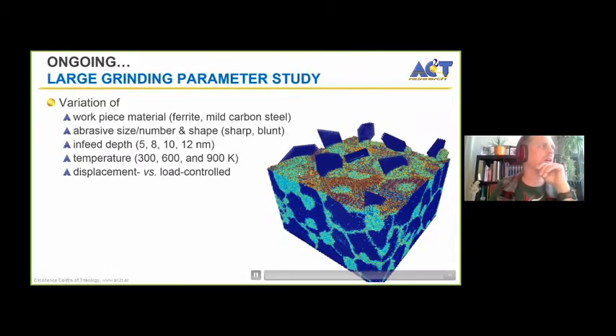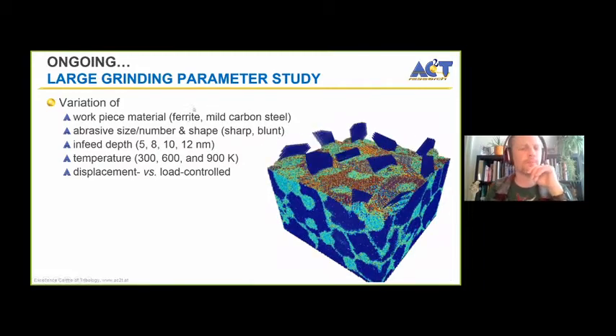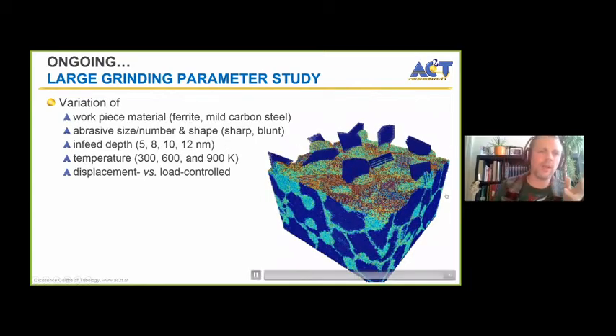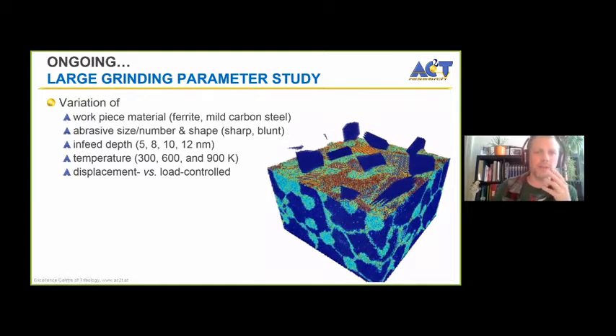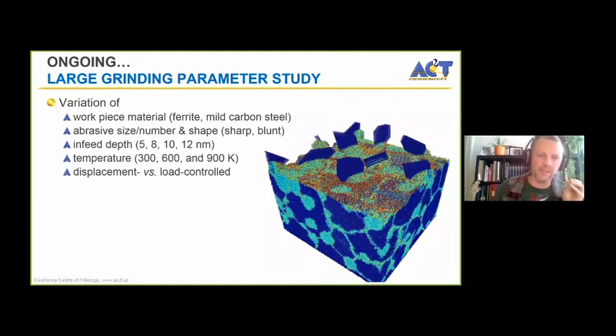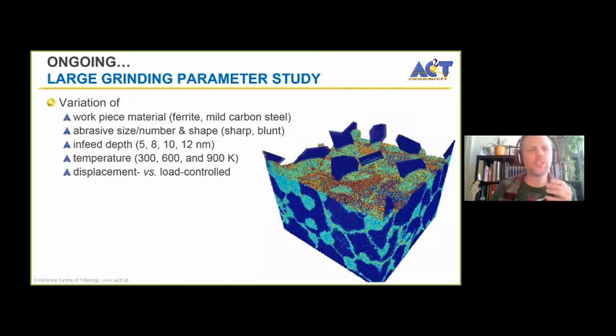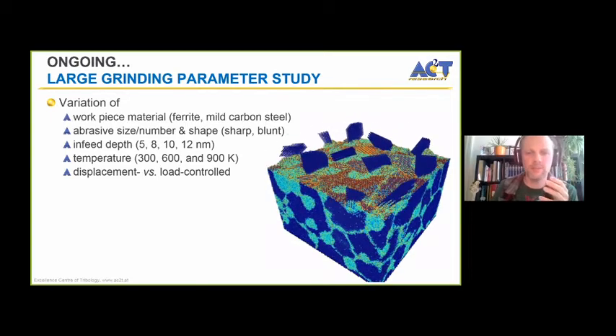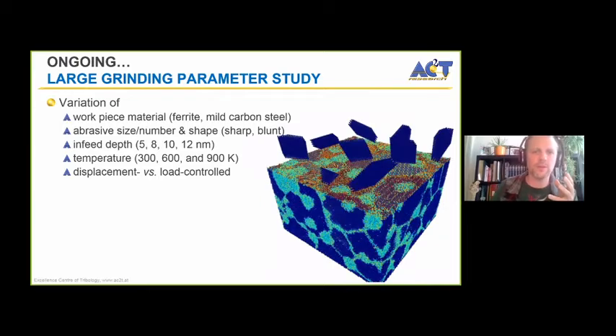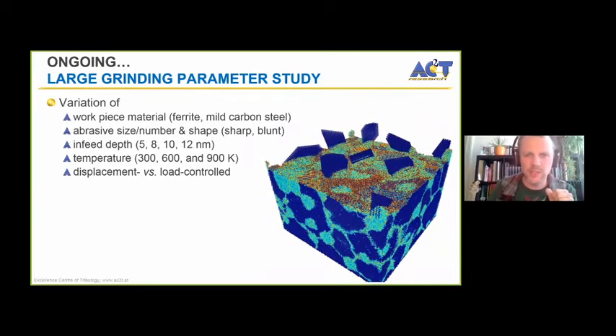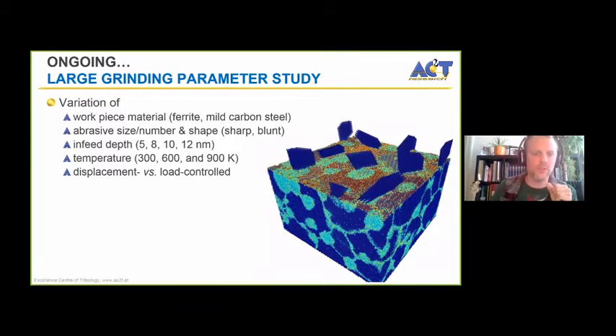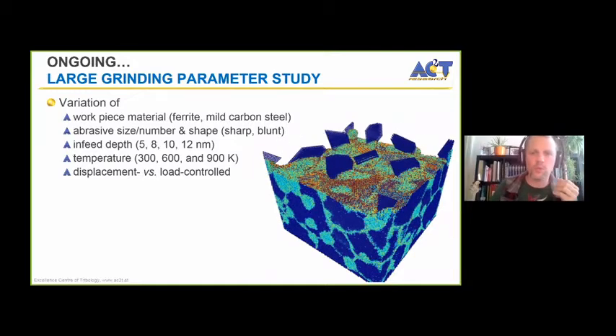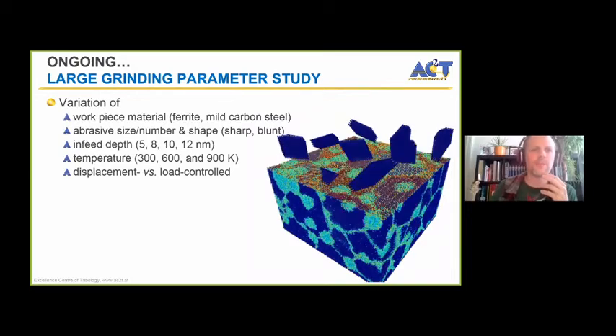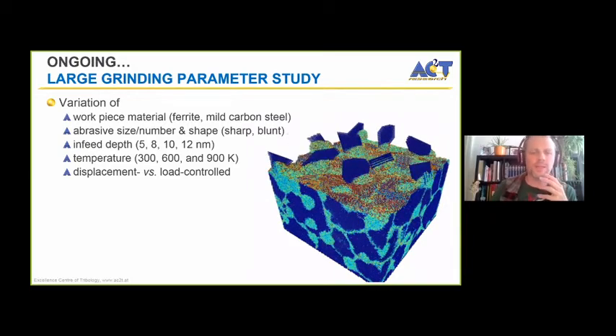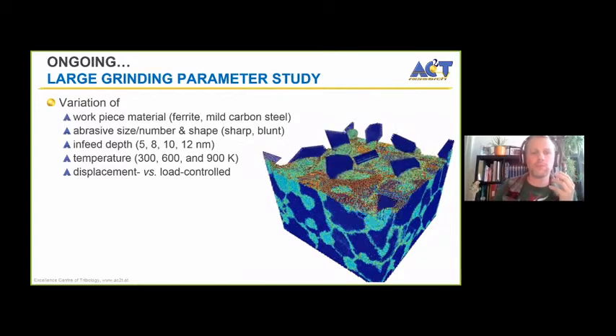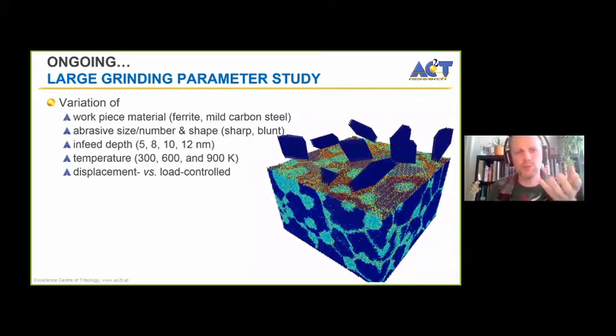And we are currently working on a large-scale grinding parameter study where we vary the workpiece material between soft ferrite and slightly harder mild carbon steel, but the same microstructure only with the second phase replaced by cementite in the steel. We change the abrasive sizes, the number of abrasives, the shape of the abrasives. We juxtapose the sharp abrasives with more ellipsoidal ones that look a little bit more like fisherman's friends. We change the in-feed depth. So of course we see if we indent further and further, how does the workpiece change? Does it change anything in the microstructure? We look at the temperature, basically a study in cooling efficiency. And we also play around with displacement controlled, where we indent to a certain depth, and load controlled.